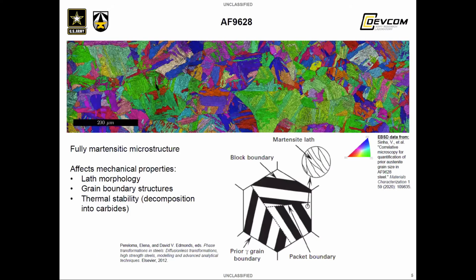Now I'd like to introduce AF 9628 as a material. The EBSD map that you see in the top shows the martensitic lath structure of AF 9628 as cast. AF 9628 is a high strength, low alloy martensitic steel. The morphology of the martensite lath and grain boundary structures in this material is what drives, as with other materials, the mechanical properties.